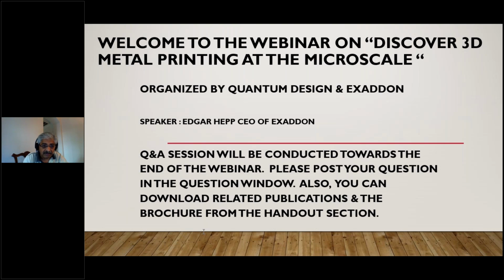Are there possibilities to increase movement speed, and is that the time limiting factor? Once again? Are there possibilities to increase the movement speed, and is that the time limiting factor? The time limiting factor for the printing speed is the electrochemical reaction. We have seen now in this presentation only 3D metal prints, but we could also dispense any kind of liquid. Some customers are dispensing other chemicals on flat surfaces. If you want to dispense an oil or a polymer or nanoparticles with a liquid carrier, the printing speed can be much higher, up to 150 micrometer per second. So it can move very fast. The stage that we have can move fast. For 3D metal printing, the limiting factor is the electrochemical reaction time.